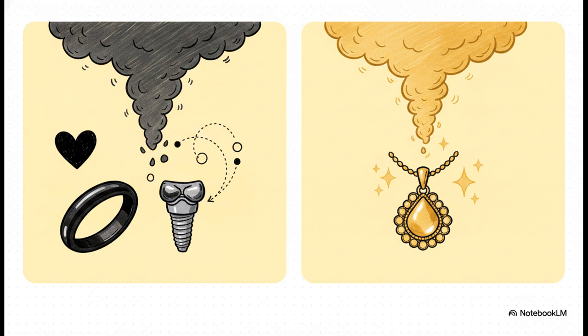Because PVD is depositing a brand new material, the coating itself determines the color. For instance, if you vaporize zirconium nitride, you get these beautiful, warm gold tones. But if you vaporize titanium aluminum nitride, or TiAlN, you achieve that highly coveted true black finish. And this specific black coating actually has a really strong clinical track record.